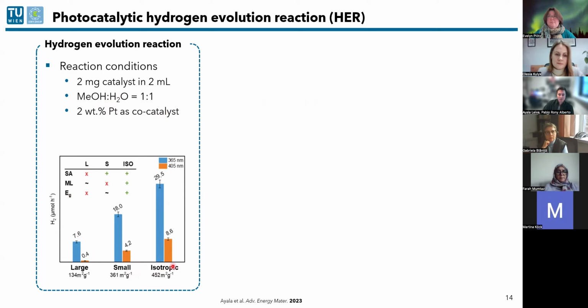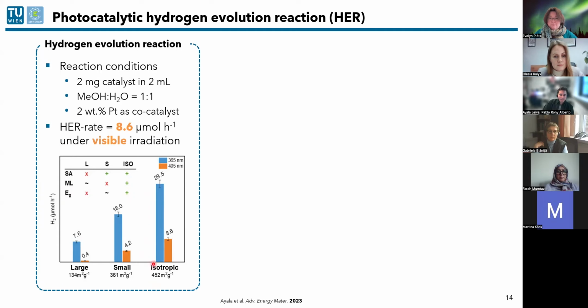So we see that this isotropic particle was indeed the best performing one under UV light, but also under visible light. And so we gave a few rough guidelines of what would be good for this reaction or in this system. So high surface area was advantageous, not having missing linker defects as well, and having a narrow band gap was also quite advantageous. And importantly, we got an HER rate of 8.6 micromoles per hour under visible light irradiation, which was one of the best performing titanium-based MOFs to date.